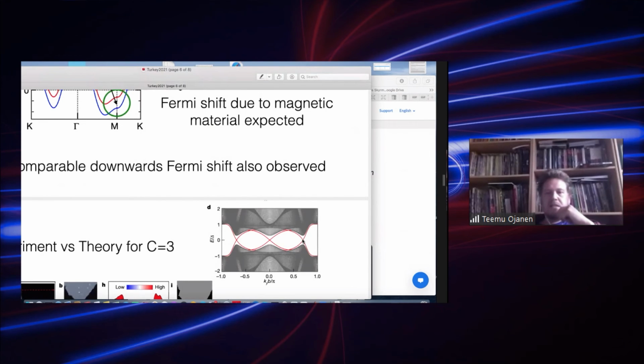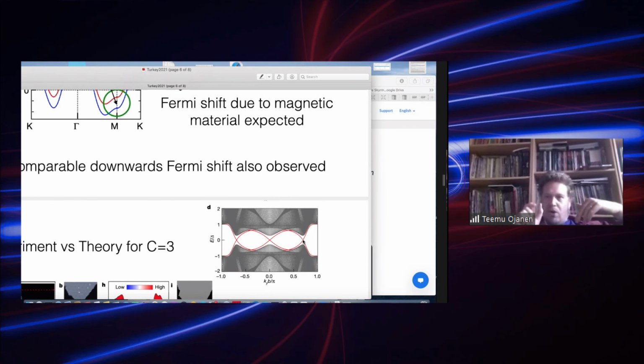So it means that the edge modes at the center of the gap are more localized to the edge. If you are measuring a local density of states close to the band edge, those modes are penetrating into the bulk a lot more than at the center of the gap. So the fact that it looks like a zero bias peak can be translated to the fact that the penetration depth of the edge mode at the gap center is much smaller than when you are going towards the edge of the gap, where they become more and more delocalized. That feature of the wave function means that you actually see this type of peak structure, and it's not constant like the density of states is.